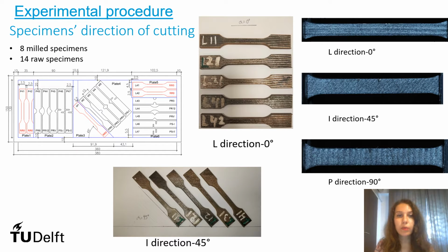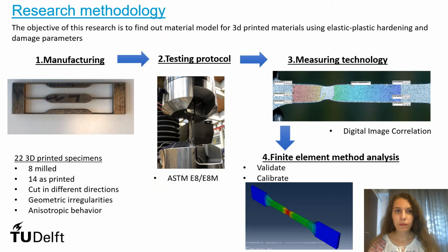Regarding the experimental procedure, 8 milled and 14 raw specimens were analyzed. We used the smallest specimen that was available in order to cut as many specimens as we could from one plate. The specimens were cut perpendicular, inclined, and longitudinal to the printing direction, and in the pictures, the roughness shows the cutting direction, which is longitudinal, inclined here, and perpendicular to the printing direction.